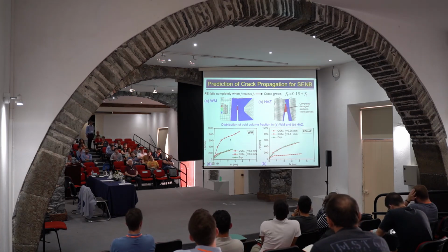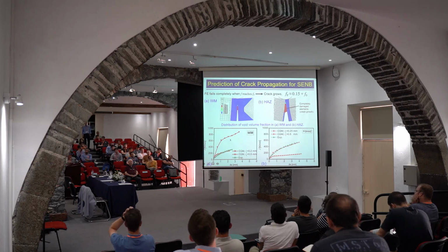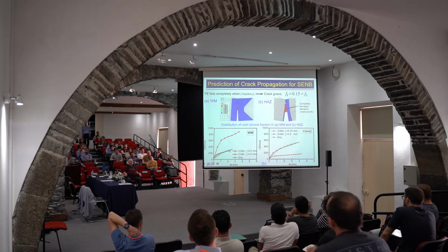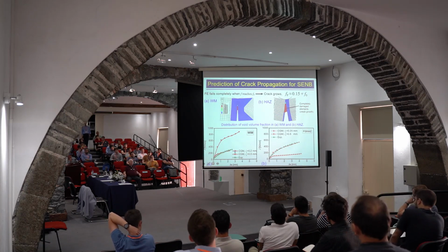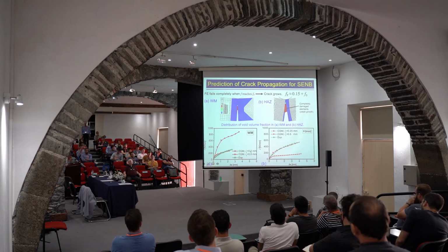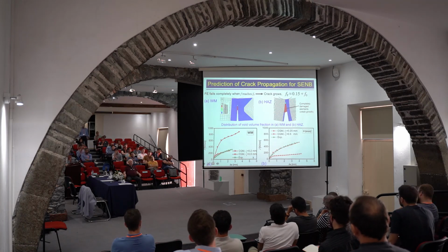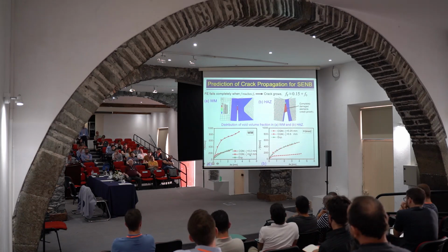If I would like to criticize this method, this micromechanical modeling, then I would have to use these slides. So here are experimental results for JR curve. And here are numerical results for JR curve if we use a mesh which is 0.2 by 0.2, which corresponds to lambda in the case of weld metal. But then again, if we use mesh which is 0.5 times 0.5, we get completely different results.